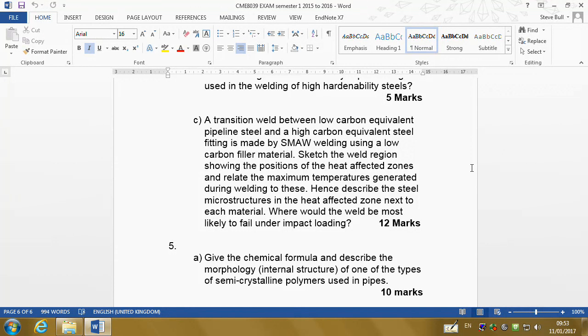Now this question says, where would the weld most likely fail under impact loading? I would say that just answering where, you could say in the heat affected zone on the high carbon side. That answers the question correctly, but you wouldn't get 4 marks for that. If you said because the weldability is poorer because of the chance of martensite formation in the high carbon equivalent side, you'd get the marks. So just answering the what without a little bit of the why, you need just 1 or 2 extra things to get the number of points that are there.